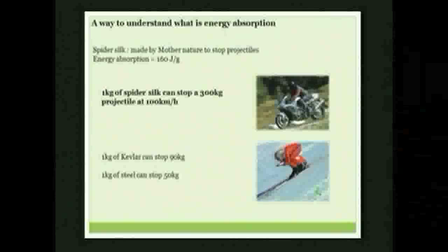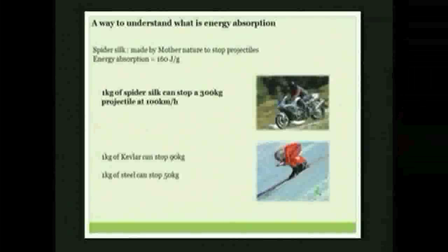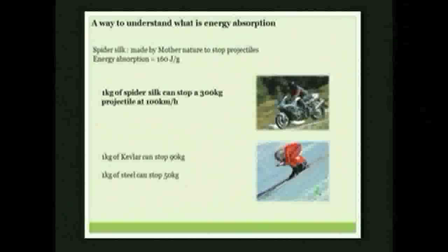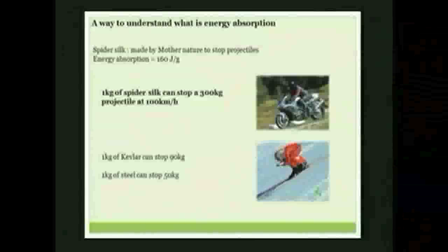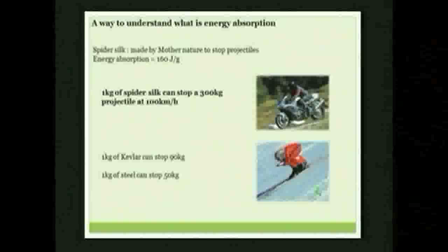Just to explain you a way to understand what is energy absorption. It's not always easy to understand exactly what it is. Let's take the example of spider silk. I said it has been made by Mother Nature to stop projectiles with a high energy absorption, 160 joule per gram. 1 kilogram of spider silk can stop a 300 kilogram projectile launched at 100 kilometers per hour. This is a way to understand what is this value of energy absorption. So a motorcycle with the man on it can be stopped. But you can imagine that to make 1 kilogram of spider silk, it's not easy because of the density of spider silk. Just to compare, 1 kilogram of Kevlar can stop 90 kilograms, and 1 kilogram of steel can stop 50 kilograms. So spider silk is a very performing material. But you've seen that our nanotube fibers are even higher than this. Okay?